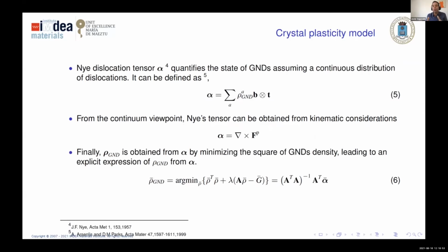They have to be there because they have to take the gradient in the plastic deformation. So how do we measure this density of GNDs? Nye proposed a second order tensor that relates to the density of GNDs. It gives us the curvatures, because curvature is what we relate with the density of GNDs. From the macroscopic viewpoint, the Nye tensor is a generalized curvature, so it can be obtained as the curl of the plastic deformation gradient. With these two expressions we can get the density of GNDs, obtained from the curl of FP.